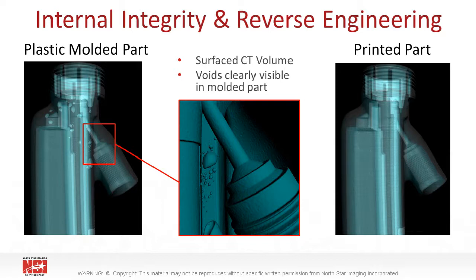In the middle, you can see these large and small voids. We're really evaluating whether or not there's any leak path that currently is occurring or something near close to the surface that could generate a leak path in the future. And then on the right-hand side, we have a printed part. We took the CT data and generated an STL from that, cleaned up the STL to remove those voids, otherwise you print those also, and then we ended up with this printed part on the right-hand side with great structure and no voids.